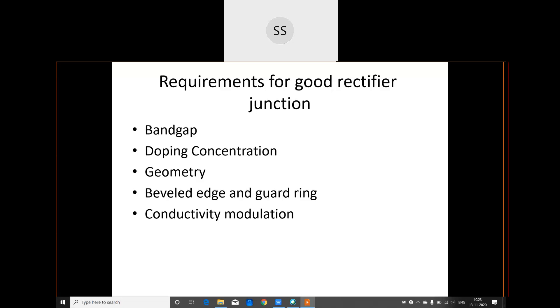A rectifier made with a wider band gap material can also operate at a higher temperature. The contact potential V-naught and the offset voltage also increase with E_g — for an increased band gap, V-naught as well as the offset voltage will increase. Therefore, while choosing any diode for rectification, band gap, its effect on V-naught, and the offset voltage all come into picture. That is why silicon is generally preferred over germanium.